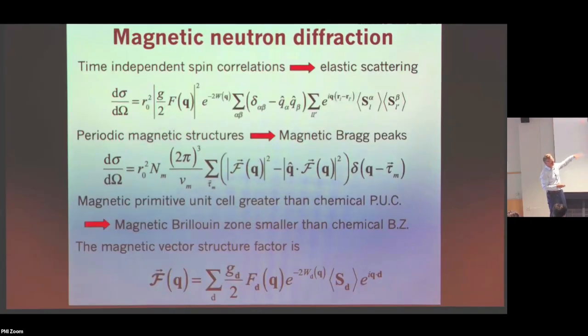Okay, now this is probably a little too much on one slide in terms of formulae, but it's mostly just to emphasize that we really know what the scattering cross-section looks like. We work with this on a daily basis at the instrument and in writing our papers. This is talking about magnetic neutron diffraction. Basically, we're learning about the magnetic structure through what we call the vector structure factor. Just like with X-rays, we have the structure factor, summing over the sites with the phase factor. With neutrons and magnetic scattering, it's actually a vector entity. So we learn something about the orientation of the spins through the structure factor, through this particular combination with the wave vector transfer. And I'm going to use that in part of the talk at some point.